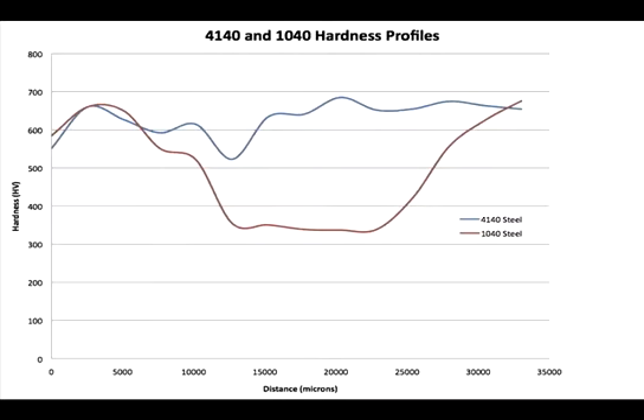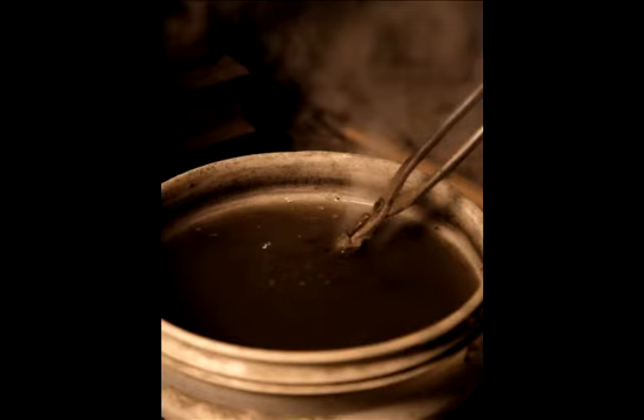As seen in this plot of hardness versus distance across a steel bar, the 1040 steel shows a drop in hardness, while the 4140 steel remains hard throughout the entire cross-section. Both steels were cooled the same way. This shows that the addition of alloying elements in the 4140 increased the hardenability.